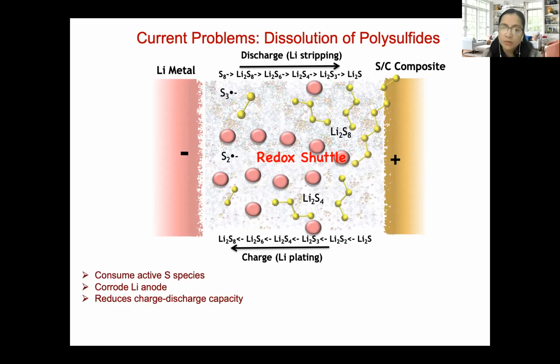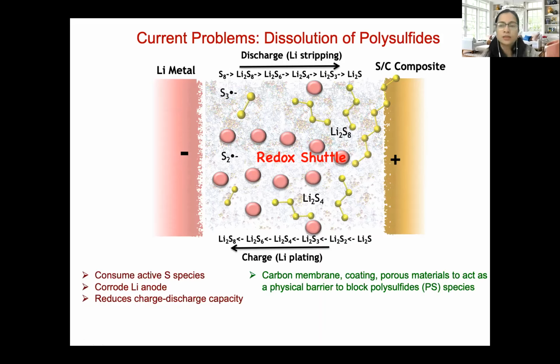And most of the effort in literature is focused on somehow suppressing these polysulfide species toward the cathode side by either using membranes or coating and porous materials, which have been successful as well. But at the same time, any additional material in lithium sulfur batteries further affects and impacts the much needed charge discharge capacity. So our approach is a little different. We are trying to design optimal electrolytes which can resist the dissolution of polysulfide species and hence suppress this redox shuttle phenomenon.